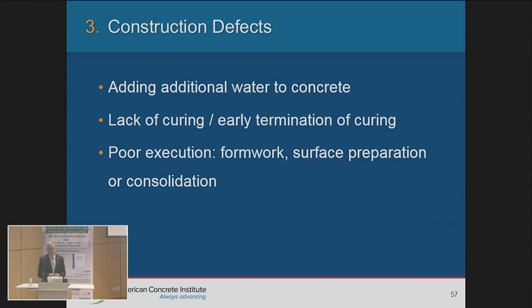Construction defects, sometimes you have during construction, you get those issues. For example, the contractor would, in order to expedite the work, make his life easier, would add water to the mix design to make it more workable. But it will change the concrete mix design and may result in untimely failure. Does not follow the curing protocol or regime strictly. That also may affect the outcome of the structure.